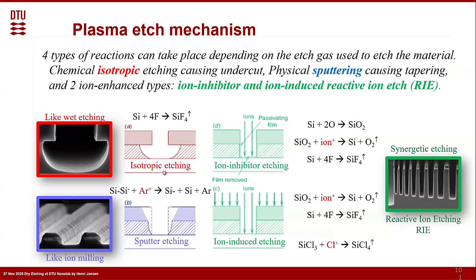The isotropic etching is more like wet etching. And a typical example is how the silicon reacts with the fluorine exothermically, creating the very volatile silicon tetrafluoride. And more an example of sputter etching is like ion milling, where, for instance, the noble ion argon is directed with high velocity towards, let's say, a silicon surface, and it just kicks out a silicon atom, which is, let's say, airborne. I would not call it volatile, but just airborne, and then it redeposits somewhere else, but you knock it out. Pure physical, this one.